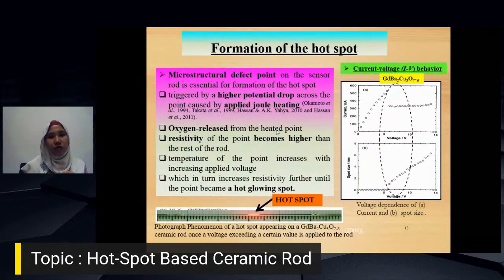Next, formation of the hotspot. Previous studies show that a microstructure defect point on the sensor rod is essential for the formation of the hotspot, triggered by the higher potential drop across the point caused by the applied Joule heating at that point. When you increase the applied voltage, the current also increases. Oxygen will be released from the heated point compared to the rest of the rod, so the resistance of that point becomes higher than the rest of the rod. When the resistance increases, the temperature also increases. The temperature of the point increases with the increasing applied voltage, which in turn increases resistivity further until the point becomes a hot glowing spot known as a hotspot. So the spot appears.